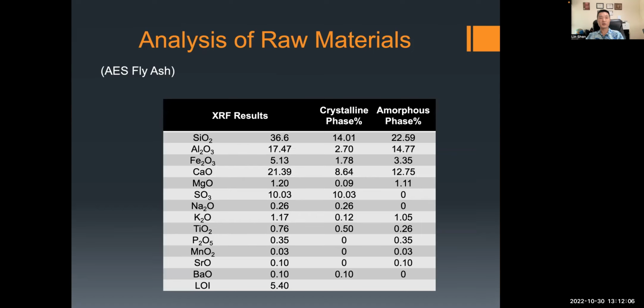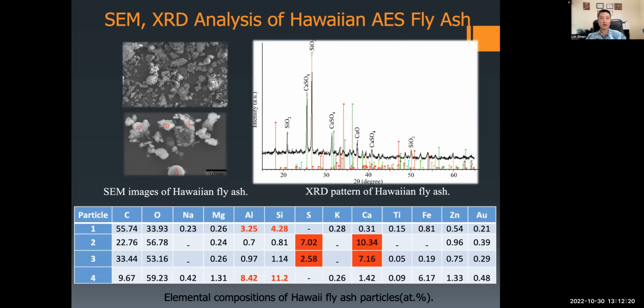And here shows the AES fly ash. AES fly ash is coming from a Hawaii local power plant. The fly ash has pretty low quality compared with commercial fly ash. As we can see from the scanning electron microscope, AES fly ash is not a classic spherical shape, and it has less reactive phases and also larger particle size.